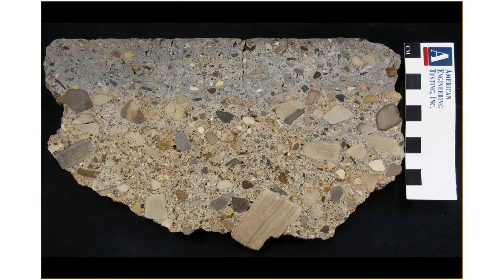The first lift of this concrete was very chunky, a very low slump, if you will. It was under consolidated, so there's a great number of consolidation voids. They're hard to see, but the very chunky nature of this concrete was due to the aggregates, the gap grading, and the low water. And so they tamped this material in place.